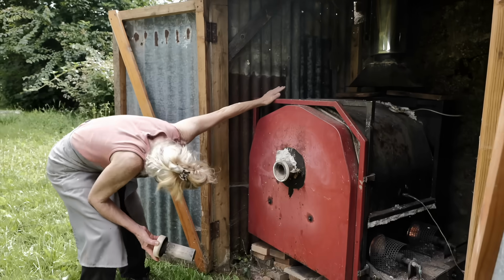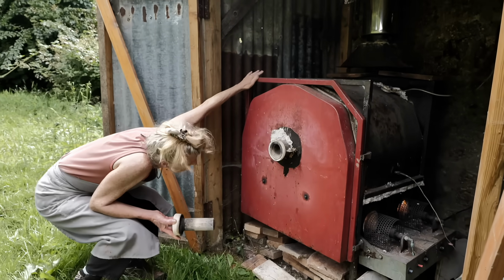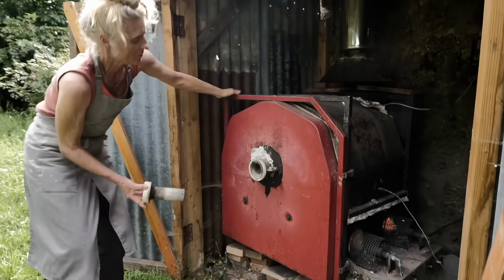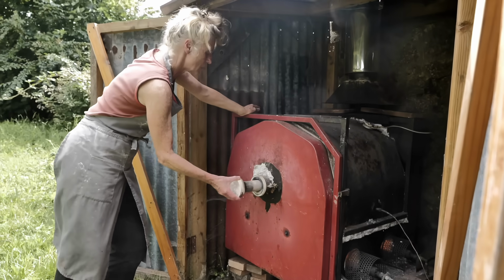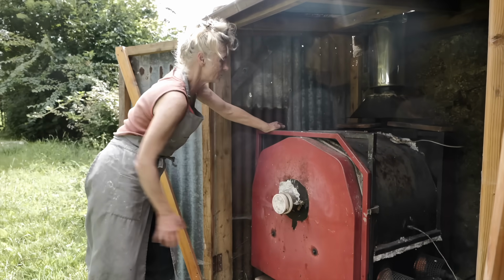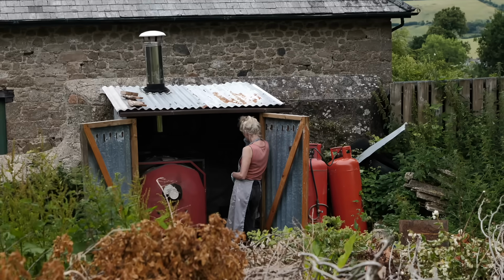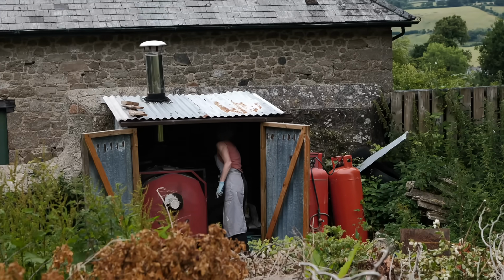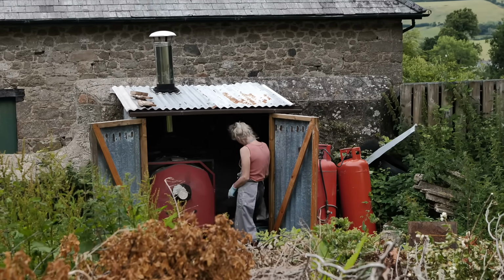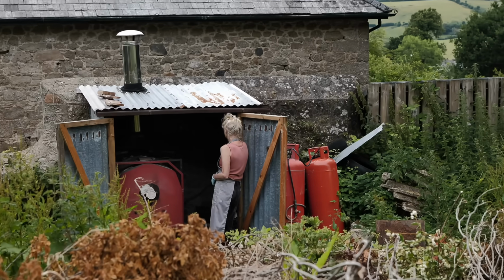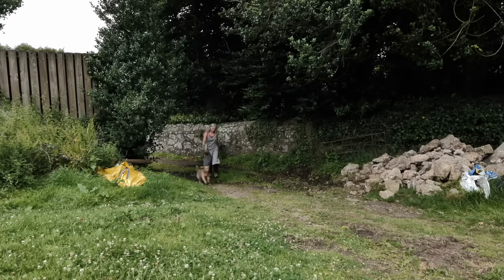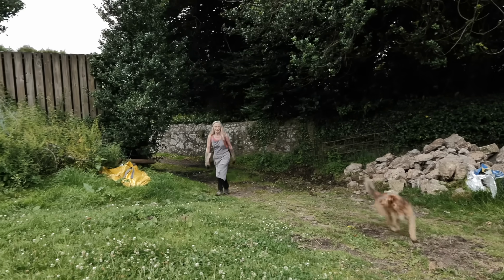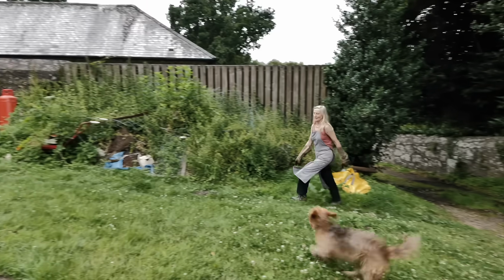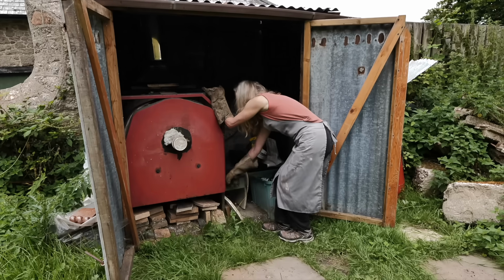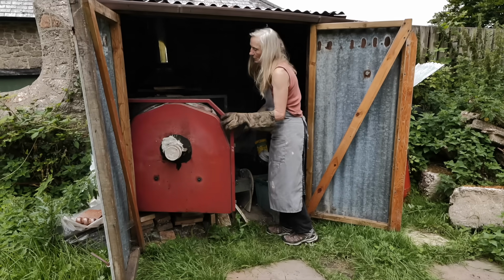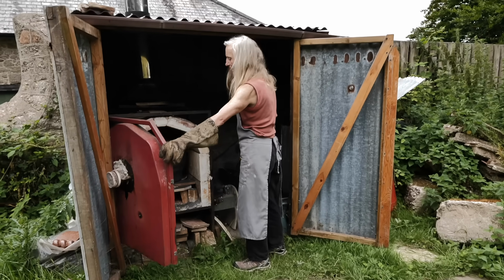I'll go into full reduction around 800 degrees. Take it up to between 870 and 900, and oxidize for 20 minutes. I hold it for 20 minutes at top temperature. I close everything down, bung up the chimney, bung up the baffle, shut my little kiln shed doors, and leave it overnight. The following morning, I will go and check the temperature on the kiln to ensure that it's cool enough to open, and we'll open it around 30 degrees if that's what's showing on my pyrometer.